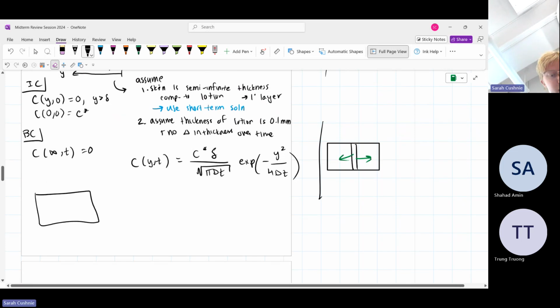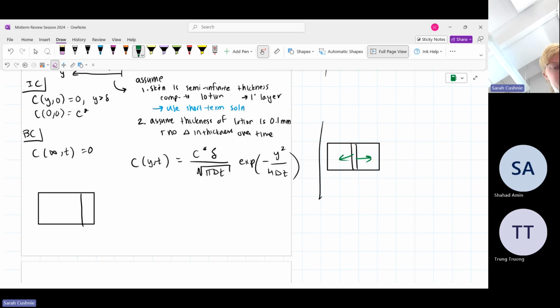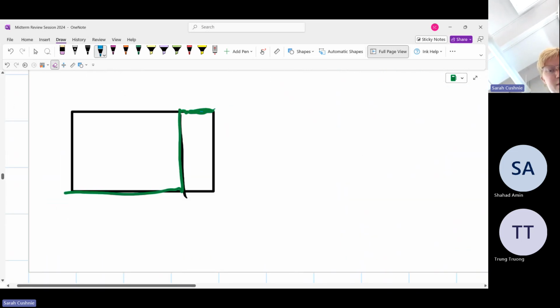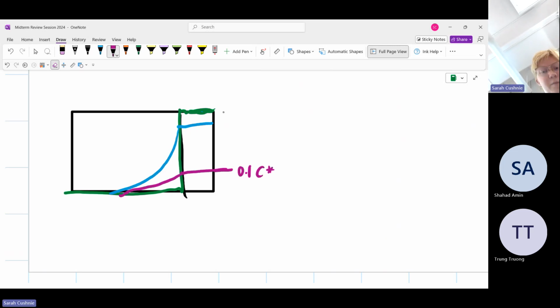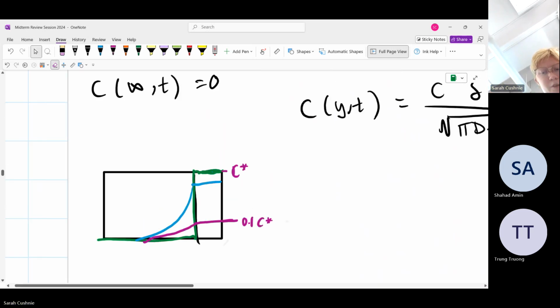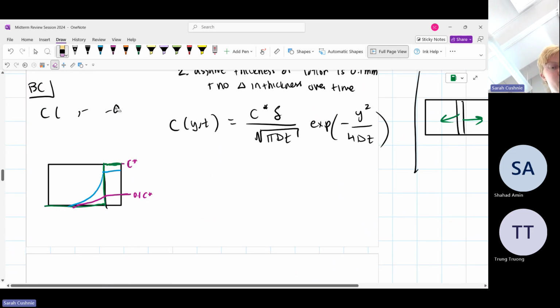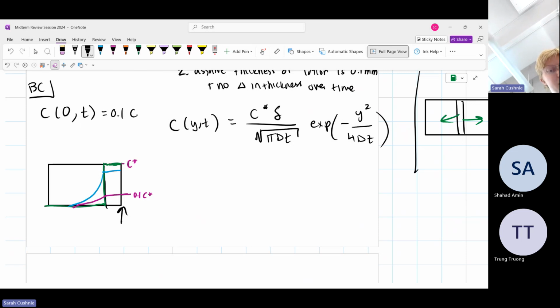Because remember, I'm going to draw what it looks like at the time we're trying to find. If it starts out like this, remember we made the assumption that it's going to be constant here. Over small time, it's going to look something like this. But we simplify it to look like a horizontal line. The time we're trying to find is at which this value here is at 0.1 C star, whereas this is C star. So we're trying to find the concentration at y is equal to 0, so right at the edge, and time t is going to be equal to 0.1 C star.